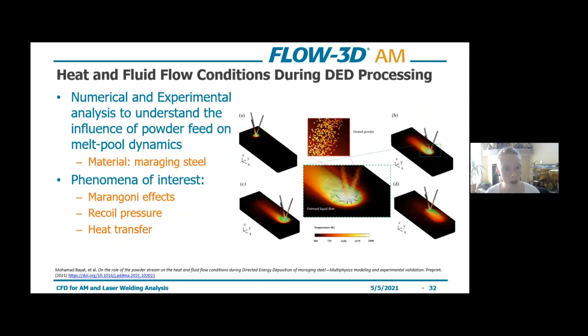And in this study from researchers at DTU, they were looking at the effect of the velocity of the powder feed on the melt pool dynamics in maraging steel, where the phenomena of interest is very much the same as other cases: Marangoni effects, recoil pressure, heat transfer, things of that nature. But something to point out here is that even when we're working with a powder feed rather than using the discrete element method to do powder spreading like we do for LPBF, we're still accounting for the powder distribution as it is in reality. And then if you have mixed alloys, as I mentioned, we can account for that as well in the powder feed.